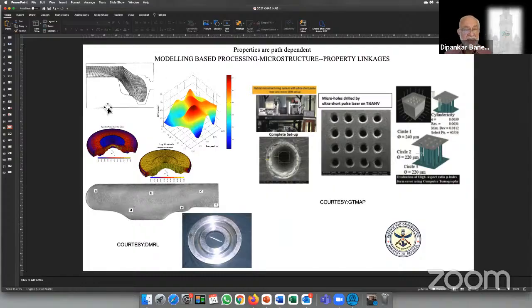So, for example, the complete die design, the materials response at different strain rates and temperatures, the flow of the material into dies, coupled with an understanding of strain rate and temperature at different portions of the component, and the microstructural inhomogeneities that this distribution might lead to, and the assessment of the final component in relation to all these operations. And this is an example of micro holes in titanium alloys for cooling of some critical parts, designed by ultra-short duration pulse lasers. And the uniformity and the materials behavior around these micro holes are a part of research that we support through our Aeronautics Research and Development Board projects.